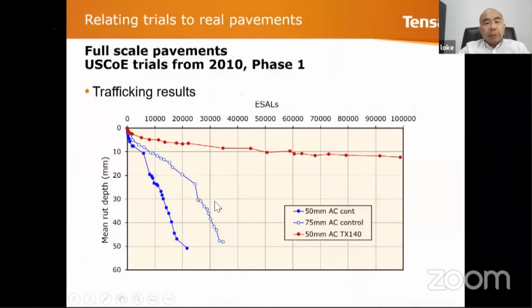Right, so this is the test and these are very interesting results. What you can see here is a control section with 50 millimeters of asphalt. You can see that the deformation, the rut depth, is 50 millimeters at only about 20,000 passes. And then you increase the thickness of the asphalt to 75 millimeters, it doesn't help at all. At 20,000 passes, it has already developed about 20 millimeters of rutting. And remember, you increased the asphalt by about 50%, and asphalt is very expensive.